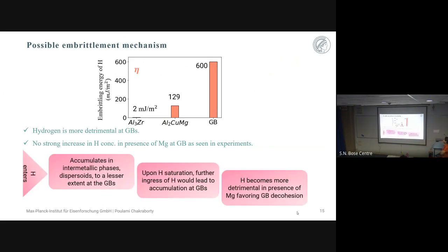So therefore, we have come to this mechanism of how the whole thing might be happening. Hydrogen is entering into the system, but due to its higher solution enthalpy in the intermetallic phases, it is first choosing to be inside these intermetallic phases, where it is getting trapped. Then the rest of the hydrogen is going to the grain boundaries. Once it is entering the grain boundaries and getting saturated there, the saturation is leading to accumulation of more and more hydrogen at grain boundaries, which becomes more detrimental because once hydrogen goes there, even in lesser quantities, the presence of magnesium favors the grain boundary decohesion, and we can see grain boundaries much more near the crack formation regions.